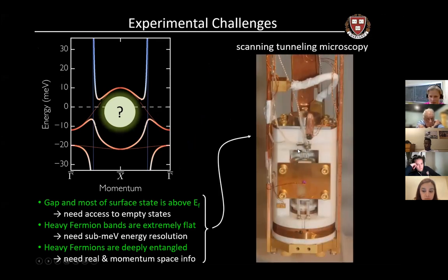I think you did a little bit of pre-work on Monday about scanning tunneling microscopy. Okay, so this is our microscope. It's about 4 centimeters across. We have a very sharp tip that's pointing up here, and our flat samarium hexaboride sample is face down here. We're going to take this tip and scan it back and forth across the sample, and at each position in space, we're going to measure a tunneling current, and that tunneling current tells us about the properties of the electrons in the material.